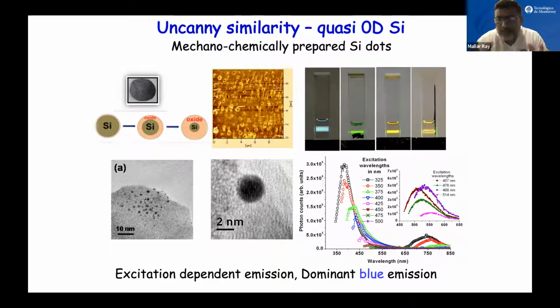I was telling you probably that my PhD and the PhD of my first PhD scholar were based on silicon nanostructures. Now these silicon nanostructures we made in a different way. We made them by repetitive oxidation etching of a ball milled sample, a very crude way of making it. But in that crude way, we could get nearly well-distributed quasi-zero-dimensional silicon quantum dots whose sizes are typically 2 nanometers to 10 nanometers. And these silicon quantum dots also emit light.